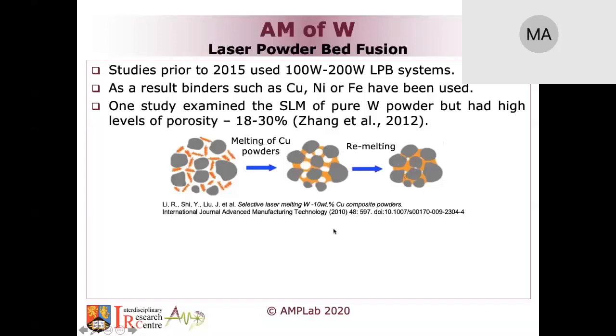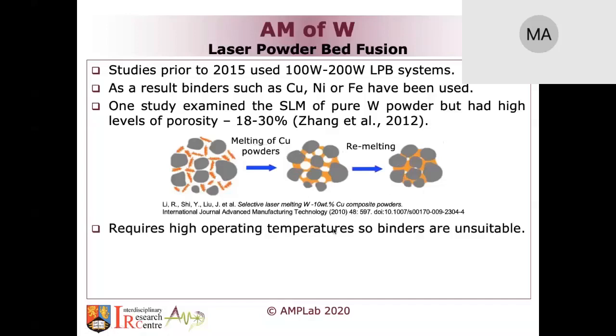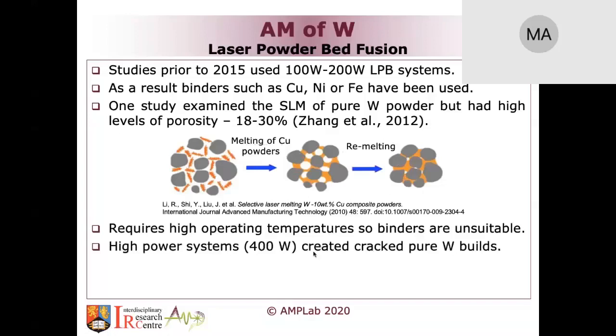But with the advancement of higher temperature machines, like higher laser power machines, the ones with 400 watts and higher, it became possible to melt tungsten, which I'll talk about in the talk. So that in a sense started to work, but the problem was that you created cracked pure tungsten builds, which was not, I would say, a surprise. We knew this is a material which is very susceptible to oxygen pickup, and it also has a higher brittle-to-ductile transition temperature, and as a result, it's likely to crack anyway.